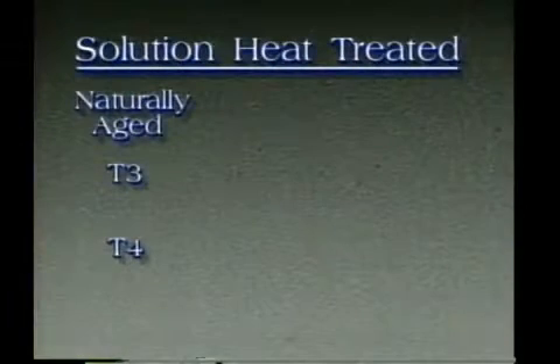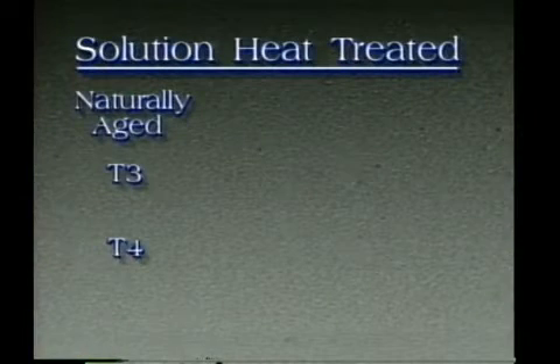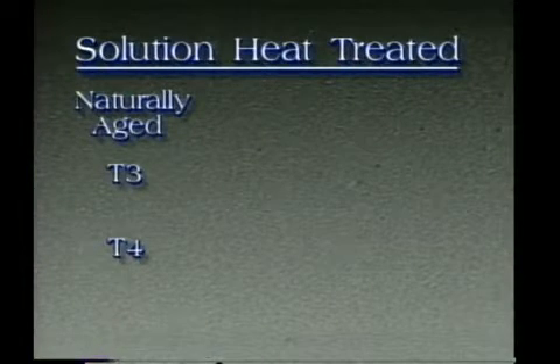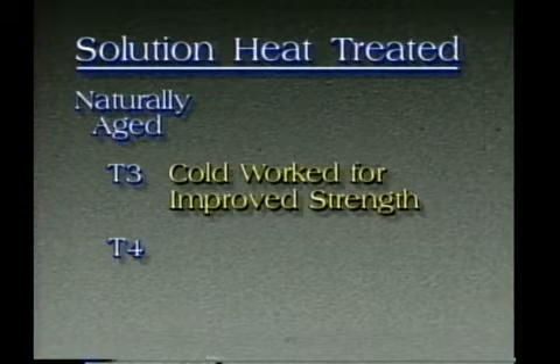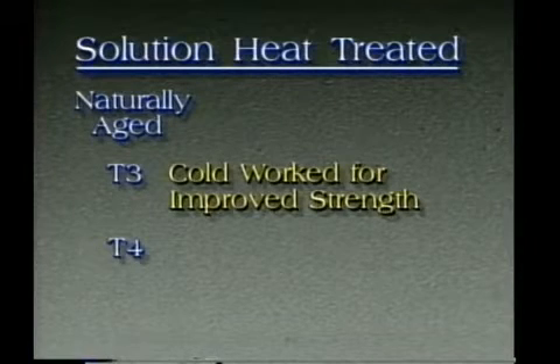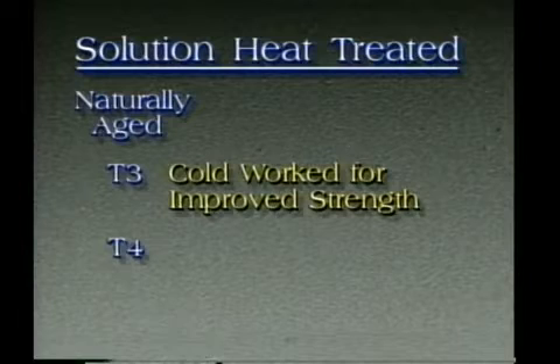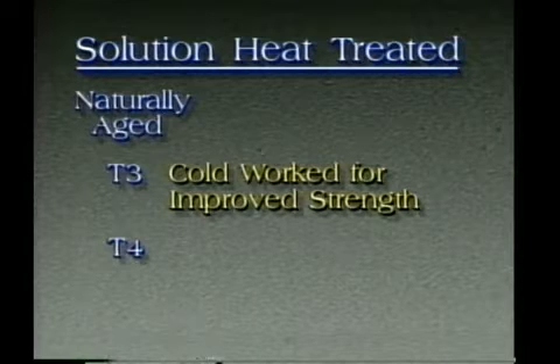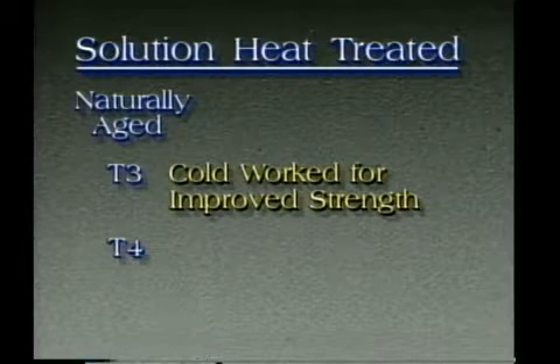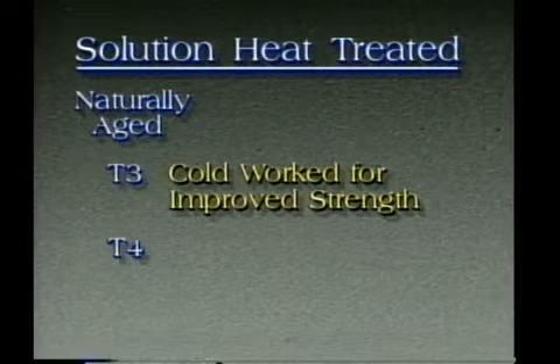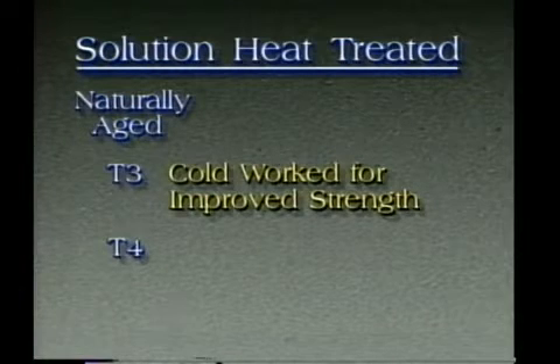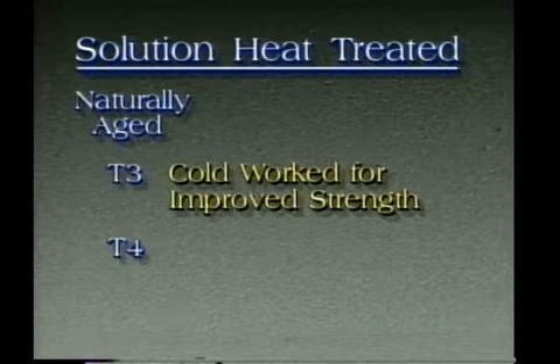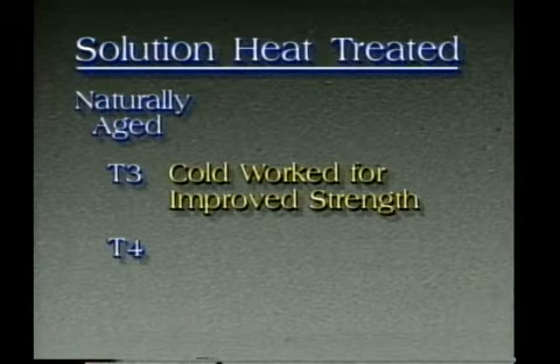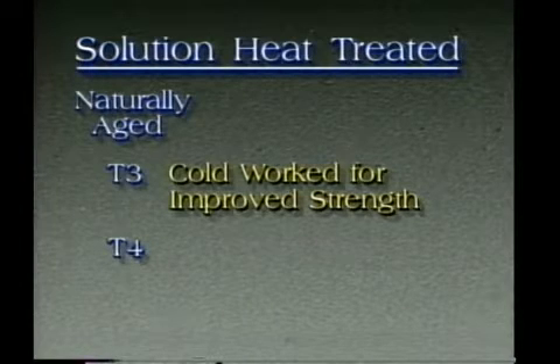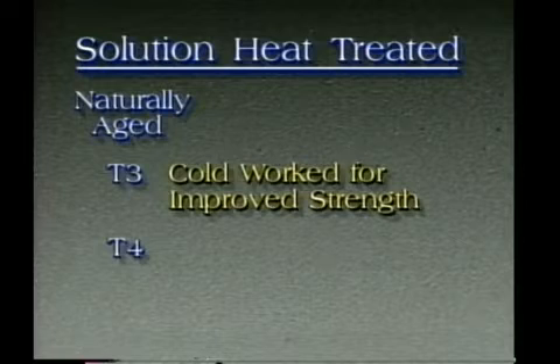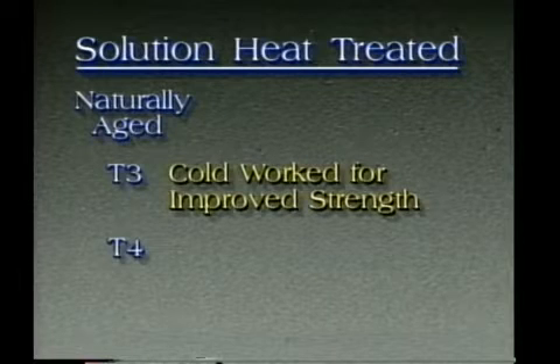The difference between the T3 and T4 tempers is that the T3 temper uses a slight amount of prescribed cold work specifically for the purpose of improving strength. This cold work is performed after solution heat treating to improve the mechanical properties. The working operation is usually performed by stretching or rolling and is normally accomplished at the primary mill. Thus, the T3 temper is rarely produced by the commercial heat treater.